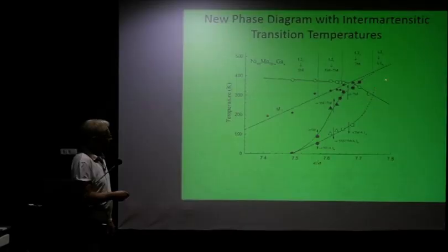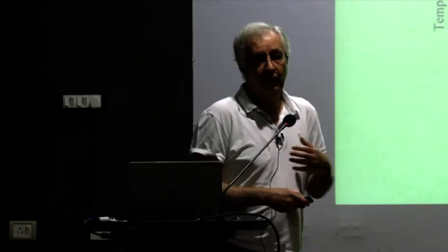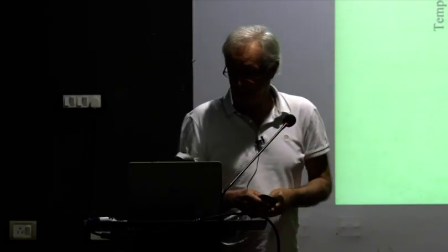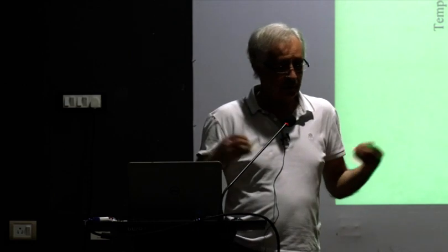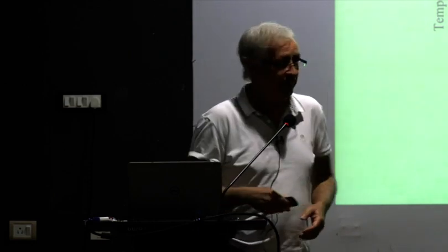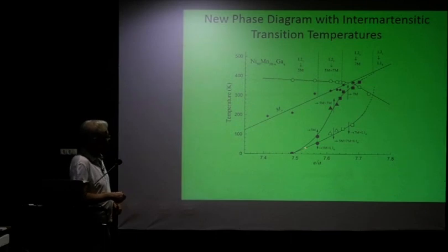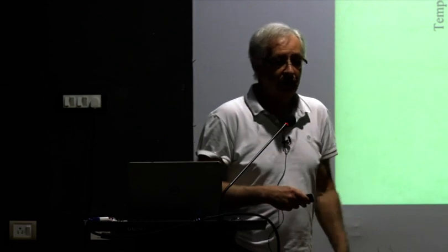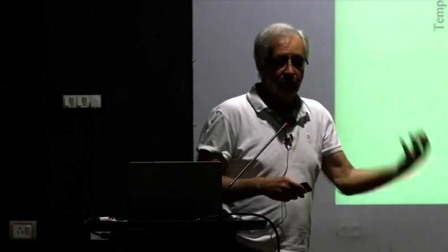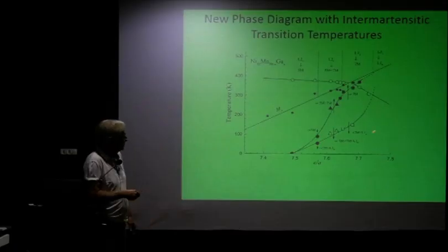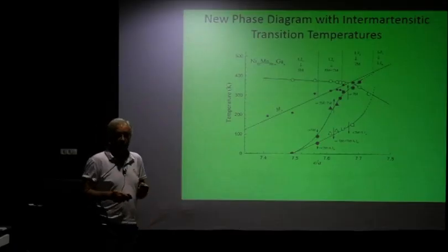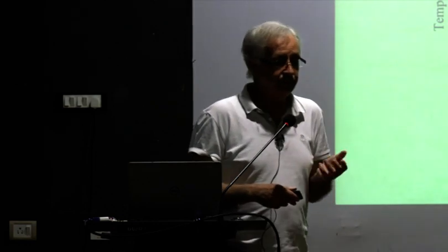So we understand from these kinds of measurements, and when we have established some kind of a phase diagram composed of several points, and extrapolating these values within reasonable limits, we can get a general picture of what is going on, and we can in fact infer that a ground state should always be L10, which is in agreement with theory as well.